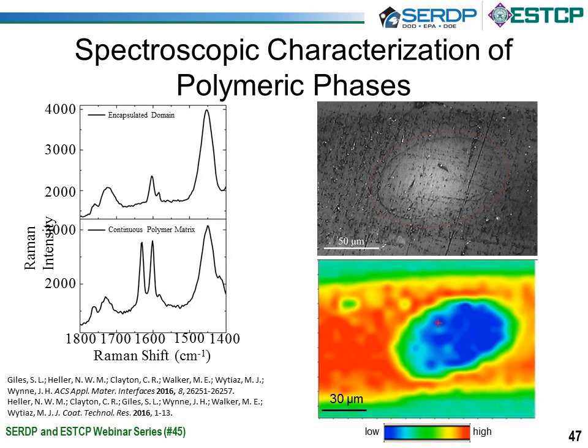However, the continuous phase of the polymer matrix has a nice handle in that it has a peak at 1632 reciprocal centimeter. This has allowed us to perform a mapping of the same sample, as illustrated on the bottom right. The map is an intensity map at 1632. You can see the top and the bottom, the outer edges of the coating system, and within the domain itself the absence or very low concentration of 1632.